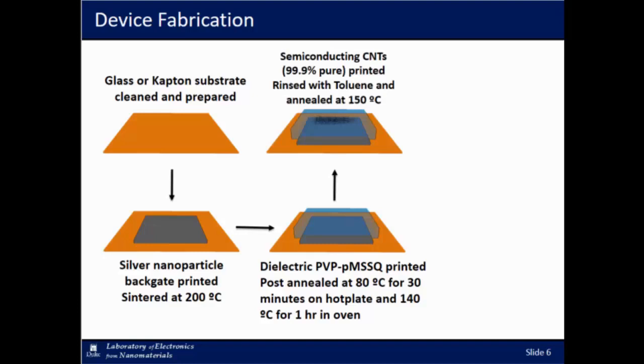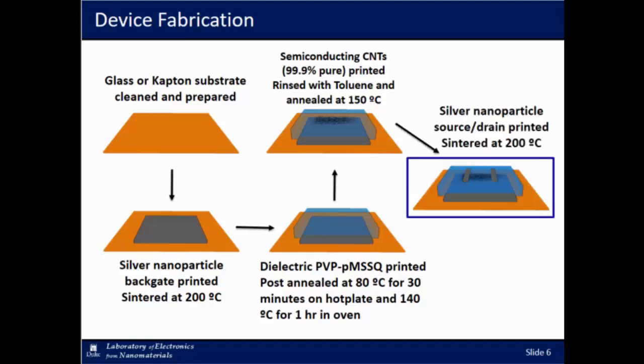For the semiconductor, we use semiconducting carbon nanotubes. They were purchased from NanoIntegris. They have 99.9% semiconducting purity. And we print those, and then we rinse with toluene, and that's to remove any leftover surfactant. And then finally, we anneal it to remove any excess solvent. And lastly, we print the silver source and drain, exactly how we printed the silver backgate.